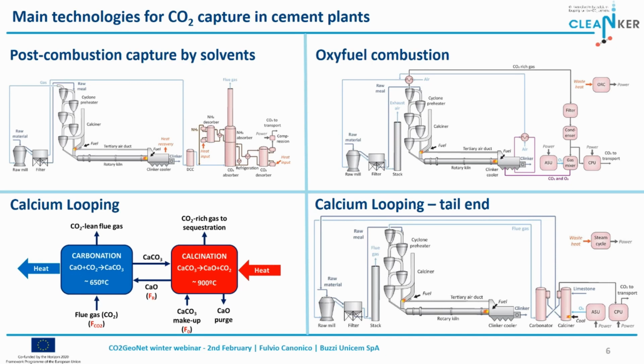An alternative solution is to go to the so-called oxy-fuel combustion. We are burning fuel in our kiln using air, so we are also injecting quite a lot of nitrogen into our kiln. So the CO2 in our emission is diluted with nitrogen, and one of the possible solutions to increase the CO2 amount is to use pure oxygen. So to replace the air with pure oxygen, and in that case we may be able to strongly increase the concentration of the CO2. This is a technology that will be tested in the next year.